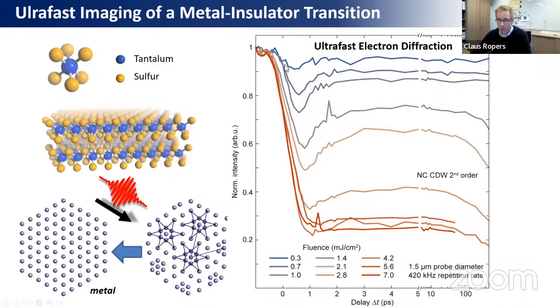At intermediate fluences, there's a partial suppression and then a relaxation back towards the initial structure. And from these time constants, you can study the type of coupling, the types of states that are initially excited and how strongly they couple to this lattice distortion and how rapidly they can relax.